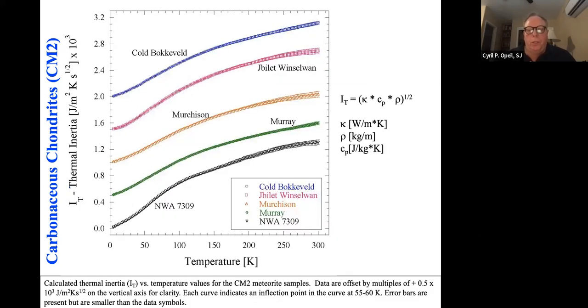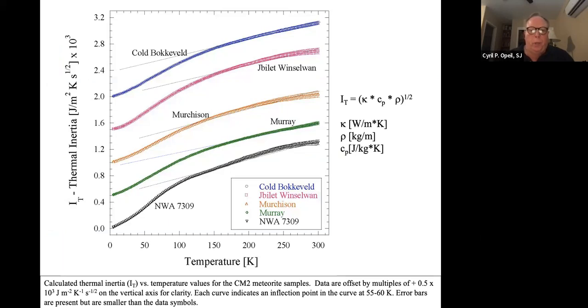Now, thermal inertia, as I said, is the resistance of a material to heat, and the numbers here on the left are times 10 to the 3. All this data is on a linear scale, and these have been displaced so that they don't all collapse onto one another. Essentially, yes, there's a general decline, and we can accentuate it using lines: around 55 to 60 Kelvin, you have an accelerated decrease in terms of thermal conductivity. But there's also an inflection point in this curve, and it's important to point it out in terms of the thermal conductivity.